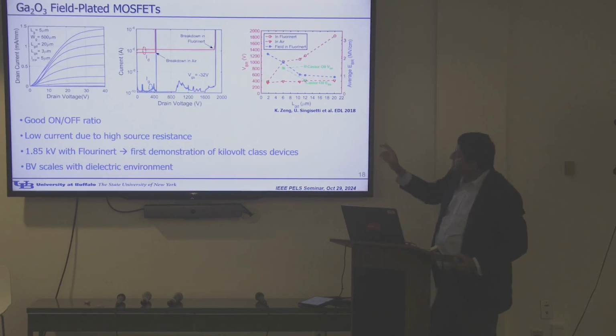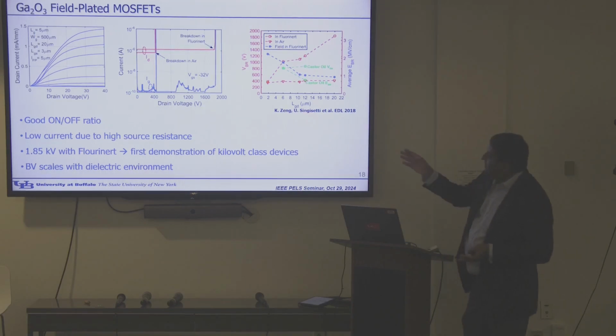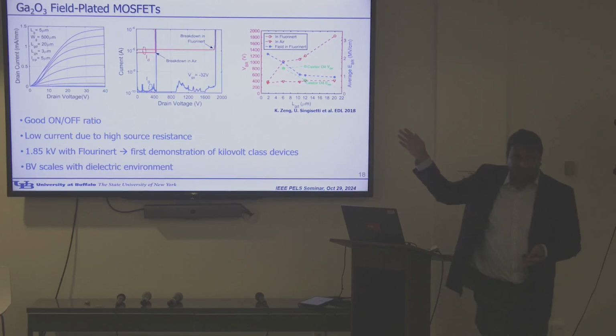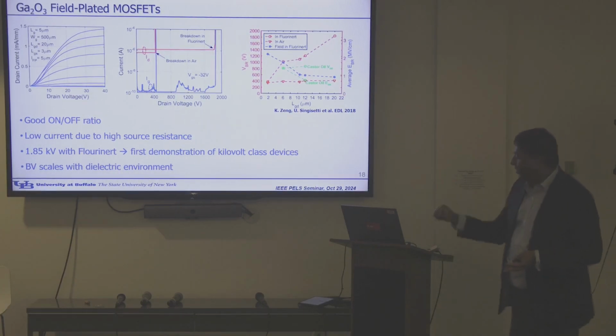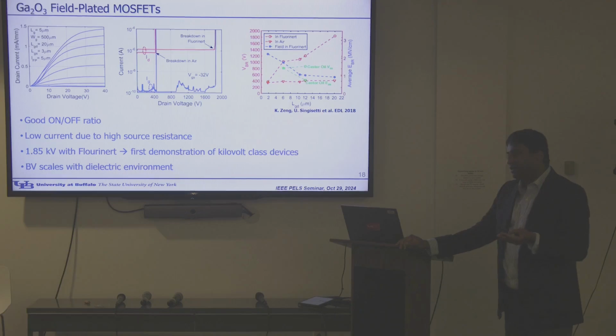And then here you can see on the figure on the left, you can see the IVs of the device. On the center, you can see when you use Fluorinert, the breakdown is 2 kilovolts, right? So this is the first time we showed a multi-kilovolt device. And I think this kind of gave a lot of interest for people to look at gallium oxide as